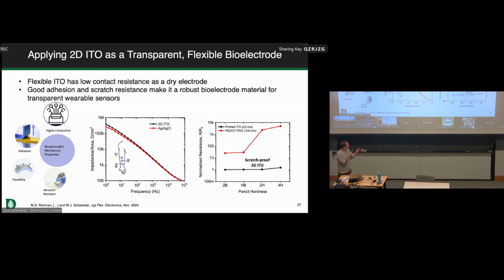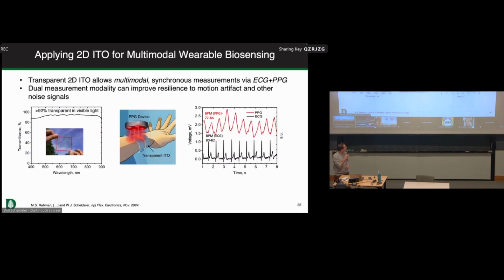It also has a relatively good resilience under abrasion. So for any wearable device, we're always concerned about the reliability. And so a material like a ceramic that has pretty good resistance to being scratched is also an ideal material for this case. But what's really interesting and what my student Cypher showed is that there's a side benefit, which is that if you're doing it with the transparent electrode, you can simultaneously collect multiple measurements, in this case, from the same measurement site. So you could have a wearable device, which is highly miniaturized to begin with, that collects a signal like pulse plethysmography at the same site as the ECG. So we're working now on essentially trying to take this method and use the fact that we have those two correlated signals to do some signal processing to make it more robust to things like motion artifact that are a challenge for wearables. And I think there's some other interesting directions that could emerge as well.